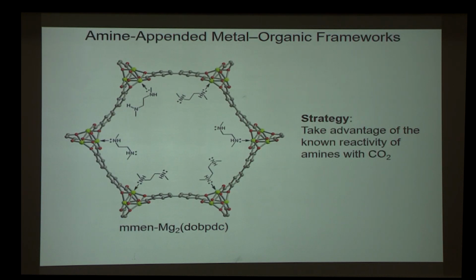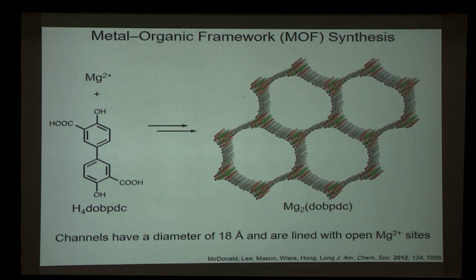The approach that we've taken in the Long group is to create amine-appended metal organic frameworks. The idea is to create a high density of amine functional groups in a three-dimensional cavity and take advantage of the known ability of amines to react covalently with CO2. The way we assemble our material is by mixing together a divalent metal cation, such as magnesium, and this organic linker called dobpdc. These building blocks assemble to create a honeycomb-type lattice that consists of hexagon-shaped channels running in the long axis of the material.